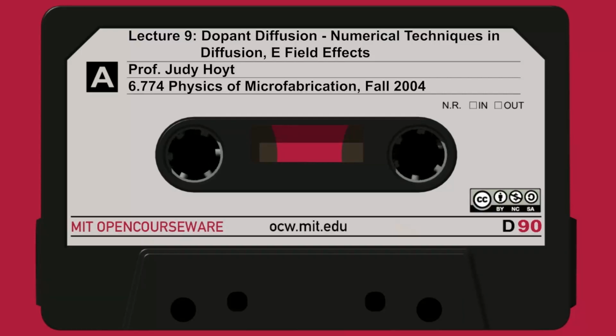So if we go on to slide number 18, we can then use that information to come up with something called an explicit finite difference formula. That's the equation being shown near the top of slide 18. What you're saying is the concentration at any given point i in one of these slabs at a new time, t plus delta t. So we're going to evolve this profile over time.